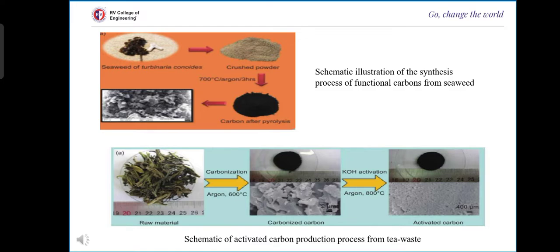And the tea waste is carbonized in the presence of argon at 600 degrees Celsius. It gives a carbonized carbon, which is further treated with KOH activation in the presence of argon at 800 degrees Celsius, giving the activated carbon.